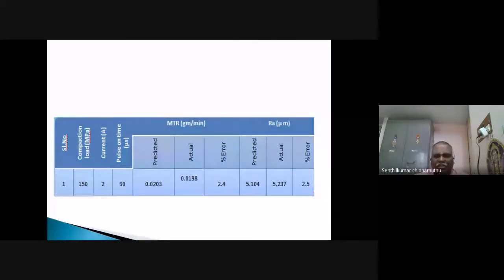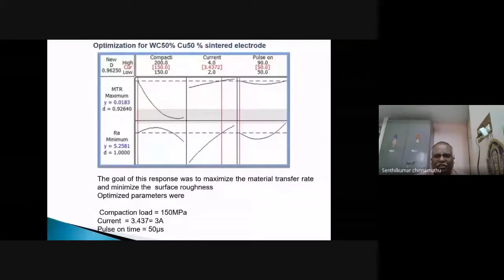Similarly, optimization for the sintered electrode, 50% tungsten carbide, 50% copper, was carried out. Finally, we have compaction load of 150, current of 3.437, pulse on time of 50 microsecond, and the maximum MTR of 0.0183 and a minimum surface roughness of 5.2581. The goal is to maximize the metal transfer and minimize the surface roughness. The optimized parameters are 150 megapascal, 3.43, approximately 3 amps, because 3.43 is not available in the machine, then pulse on time of 50 microsecond.